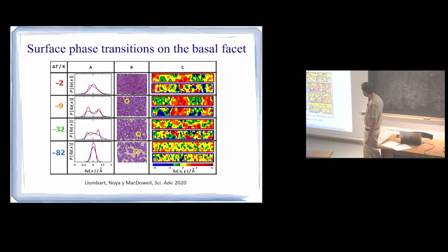Here, what I'm showing you are snapshots of a contour map. It's a contour map of the surface heights. When I am in this bimodal region, this is a real space contour map. My surface shows correlated up and down steps. This is a terrace up, this is a terrace down, terrace up, terrace down. I get large correlations of steps that are formed.